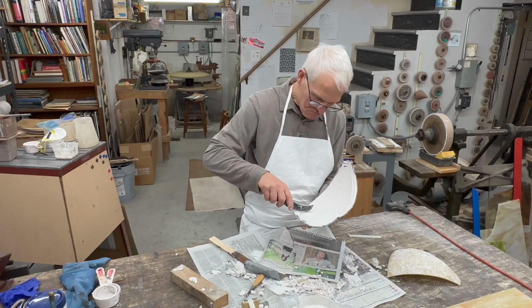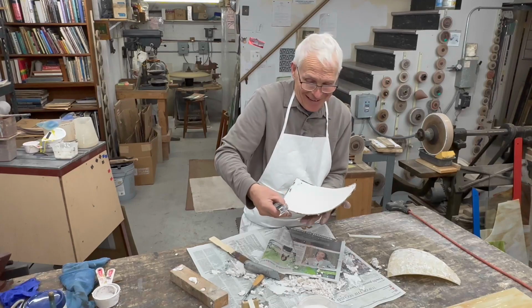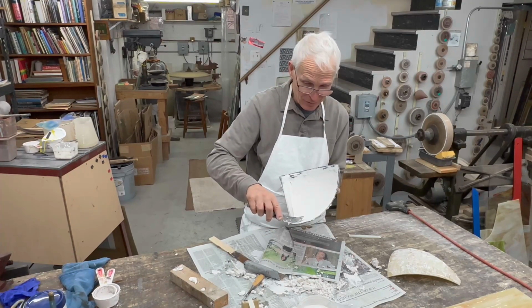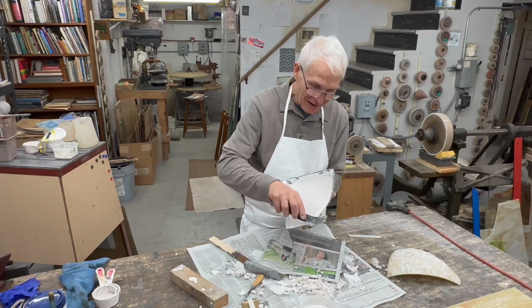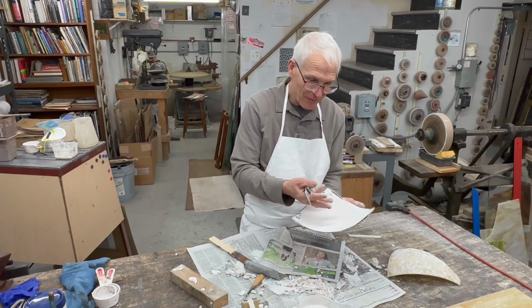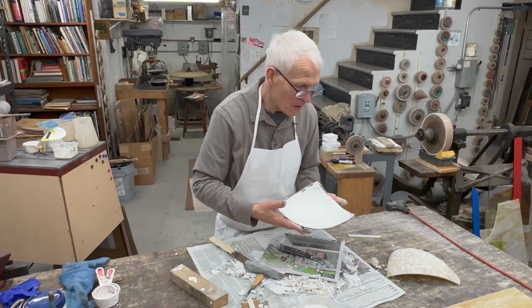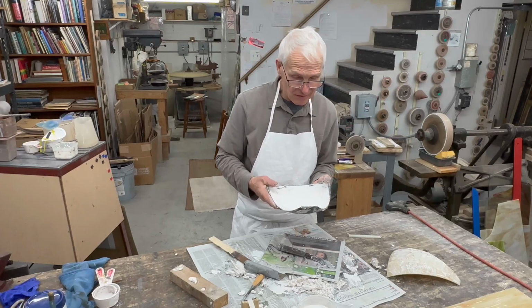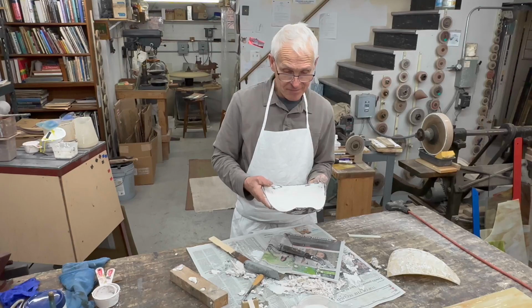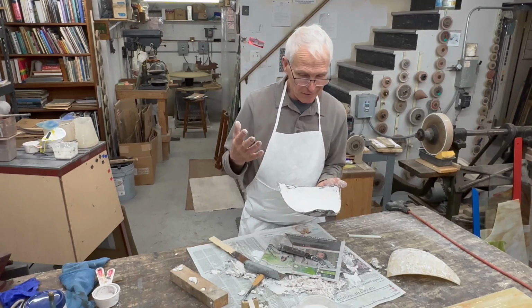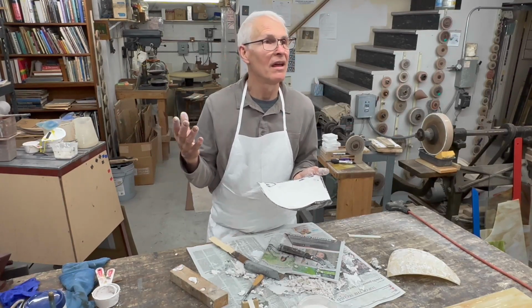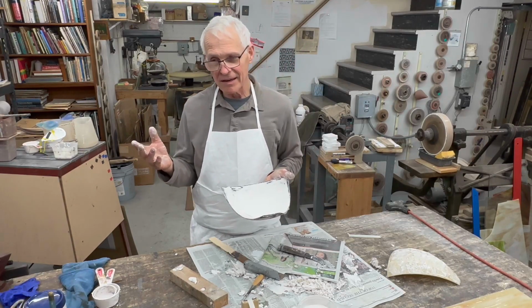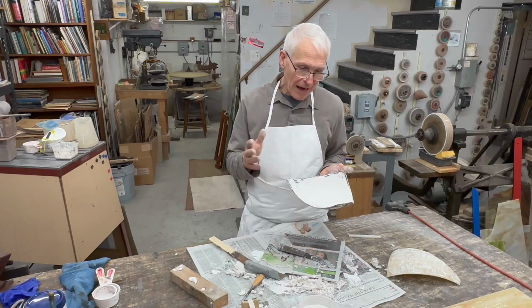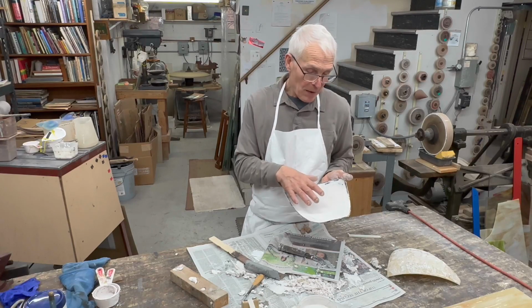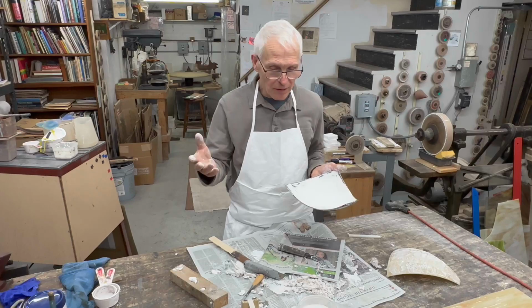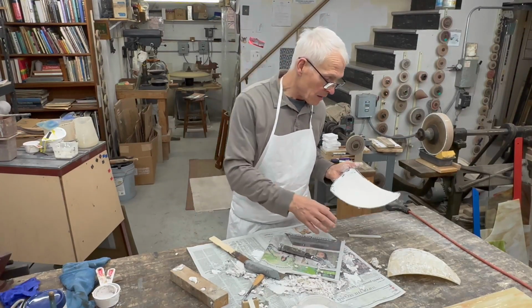I have made these where they've been perfect, you know, but there's so many variables beyond belief that you can't fully understand why it turns out exactly the way it does. But this is a suitable mold. It's going to work fine for the 4 duplicates we need to make. So we're going to put this in the kiln and dry it with a ramp rate of 300 degrees per hour up to 750, and maybe hold it for 20 minutes and let it just cool. So usually I do that at the end of the day after I've made the molds, and the next day I'll pull them out. They're dry, they're cool, and they're ready to use.